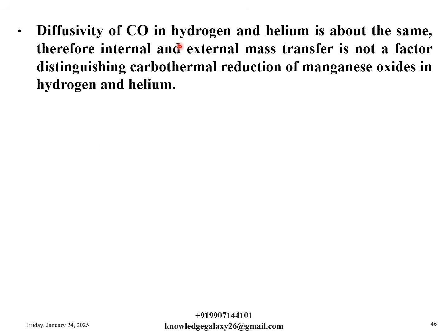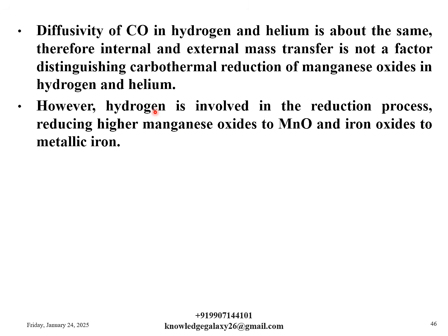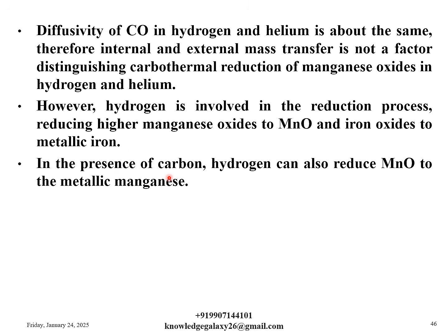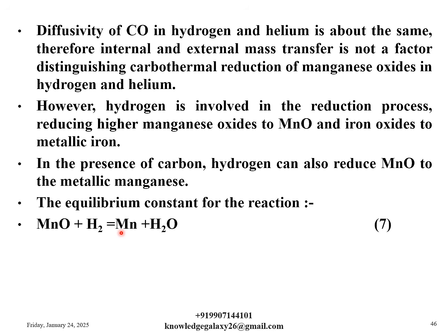Diffusivity of carbon monoxide in hydrogen and helium is about the same. Therefore, internal and external mass transfer is not a factor distinguishing carbothermal reduction of manganese oxides in hydrogen and helium. However, hydrogen is involved in the reduction process, reducing higher manganese oxides to MnO and iron oxides to metallic iron. In the presence of carbon, hydrogen can also reduce MnO to the metallic manganese. The equilibrium constant for the reaction MnO plus H2 gives Mn plus H2O. This is the equation number 7.